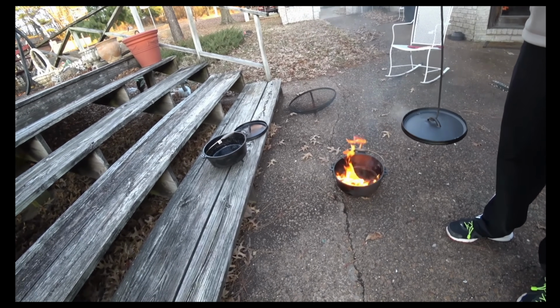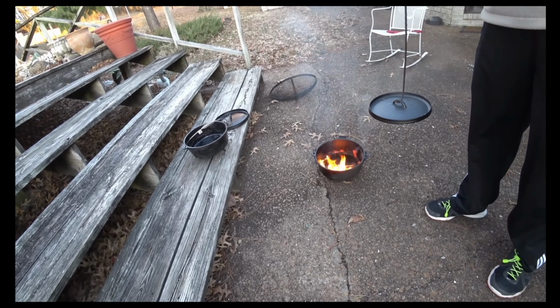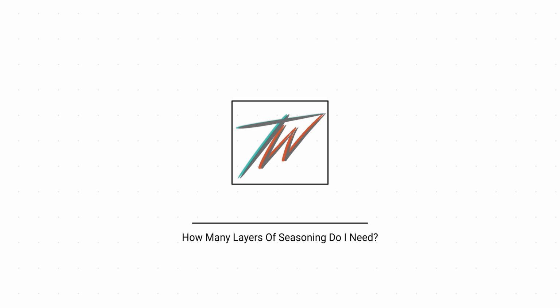There's no reason to go that macho. Actually, in the video, when he flips it over, a bunch of ash falls out. And of course, when he does the egg test, the egg has a bunch of black flakes and so forth. You can literally see that the oil burnt and it started to flake off. He thought he was seasoning, he was not seasoning. If you see flames shooting out of your pan, you're no longer seasoning or polymerizing the oil, you're literally just setting it on fire.